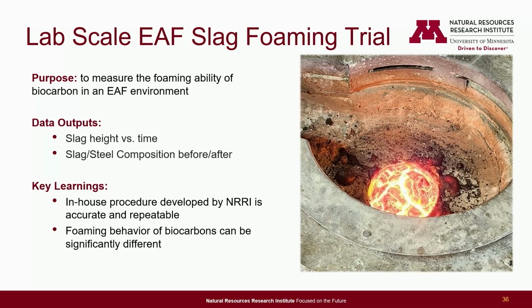We also developed an in-house procedure for slag foaming. We can actually measure the slag height over time, and then we also sampled the slag and the molten steel before and after we added the carbon. What is the binder? We played around with a couple different ones, but they are natural binders. We can talk more on the side, but yeah, we play around with mostly natural binders that are available commercially too, so it's not some secret binder that we have in our lab. It's commercially available.